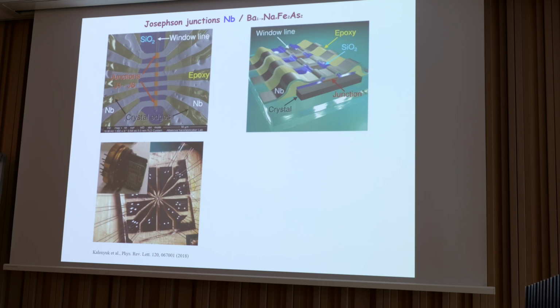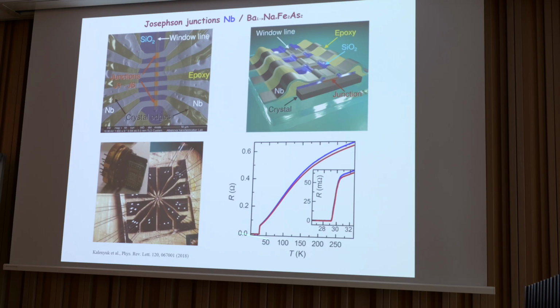So we can measure longitudinal resistance. And by sending current through the junction and measuring on this side, we can probe the C-axis Josephson properties of those junctions. So here are longitudinal measurements of resistivity. You can see the transition from room temperature. TC is around 30 Kelvin. So everything is more or less as we expected.